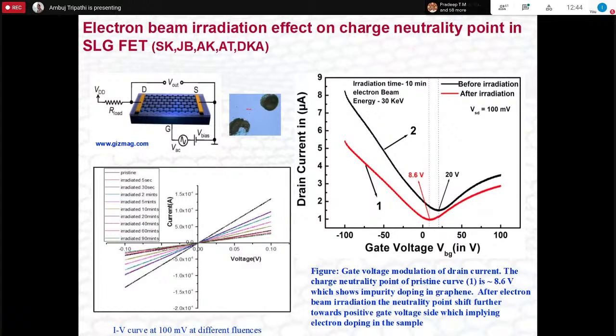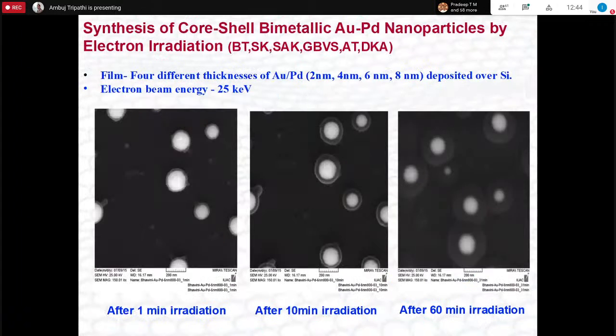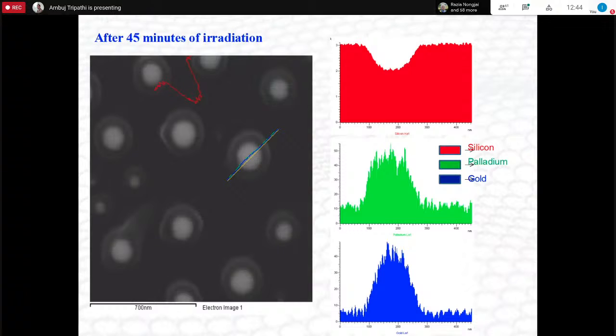Some other interesting thing we had done was on the core shell bimetallic structure. So these are the SEM measurements where you can see this core and shell. And then we had done this measurement. With SEM, you can also do this elemental analysis, so you can show what is the core part, what is the shell part.